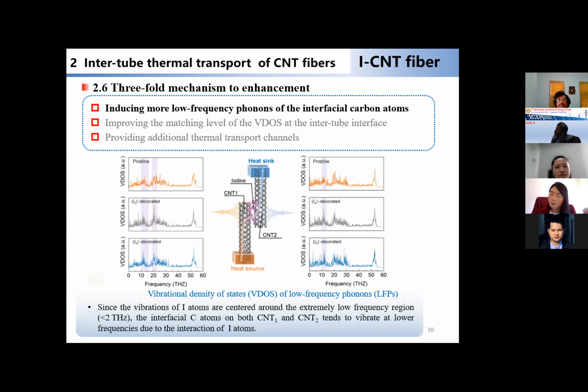By MD simulation, we further attribute a three-fold mechanism to the enhancement for iodine decorated fibers. One is to induce more LFP, just like gold nanoparticles, in the interfacial carbon atoms. Since the vibration of iodine atoms is concentrated around the extremely low frequency region, less than 2 THz, the interfacial carbon atoms on both tube 1 and tube 2 tend to vibrate at lower frequency due to the interaction of iodine atoms. This is the first mechanism.